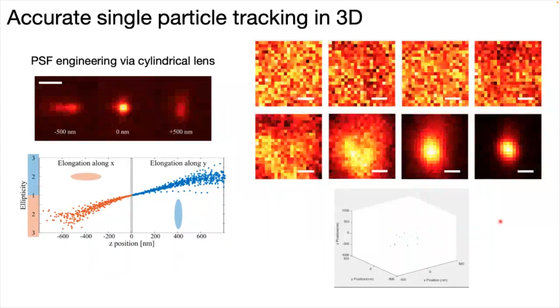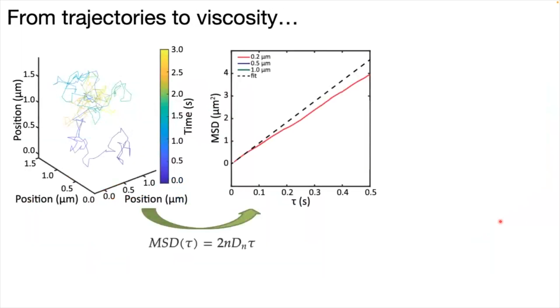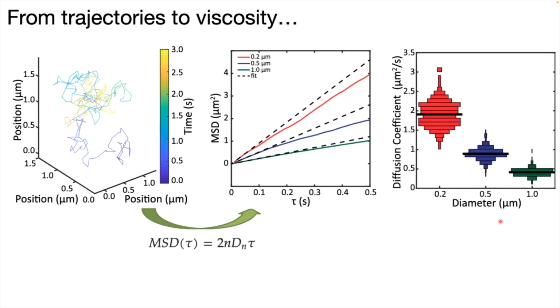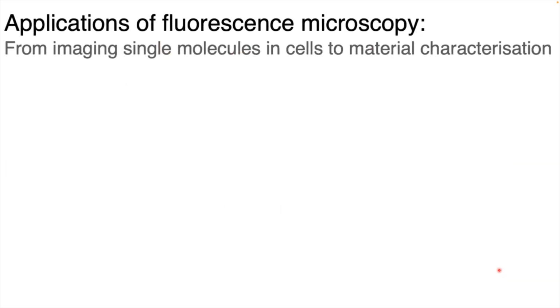And then we use that to do tracking in 3D, and from that tracking in 3D we can calculate mean square displacements, and from the mean square displacements we can calculate diffusion coefficients, and from the diffusion coefficients we can calculate, in this case, the viscosity. If we have a hydrogel that has also an elastic component, we can also calculate the viscoelastic properties. And that was it. I think I made it nicely in time.